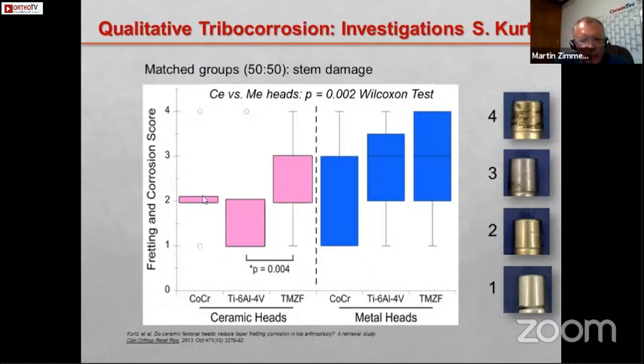If you look now more specifically at the material of the stems, which is shown here, if you use what we call the conventional titanium aluminum alloy with vanadium, we have much less fretting corrosion than with the TMZF, which is also called the beta titanium, which is a more flexible alloy and was creating a lot of fretting corrosion.